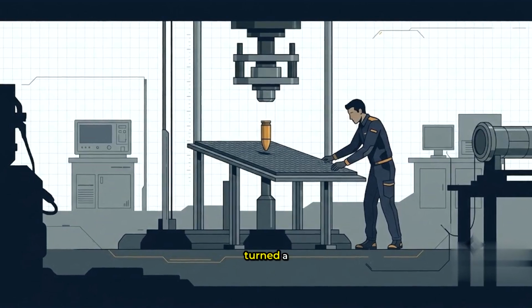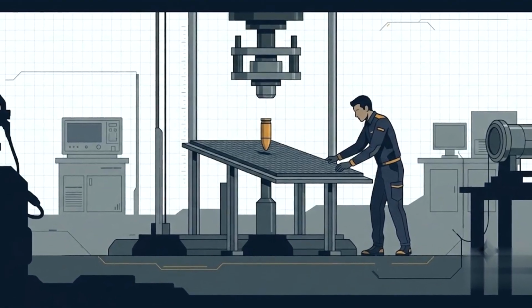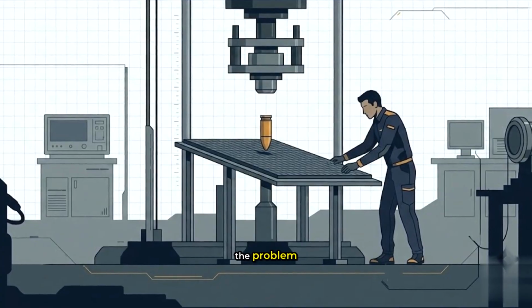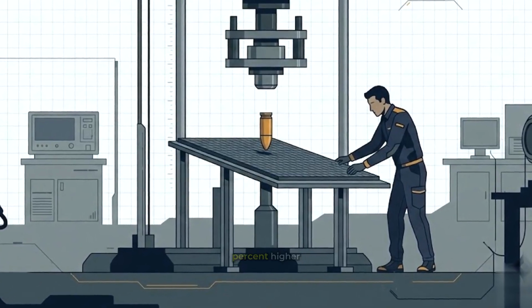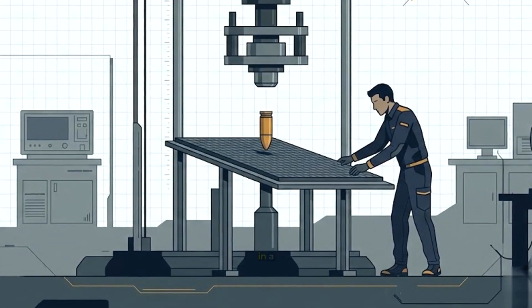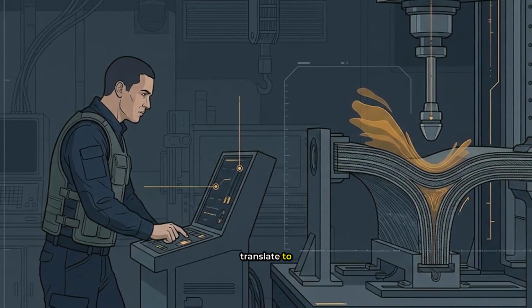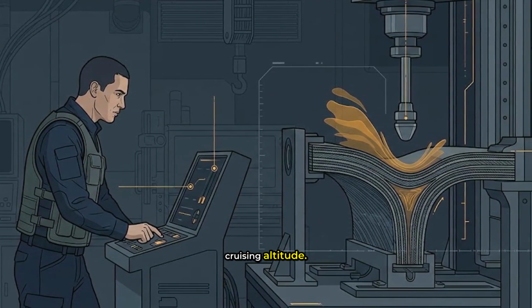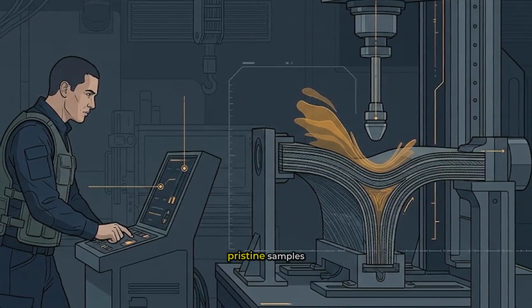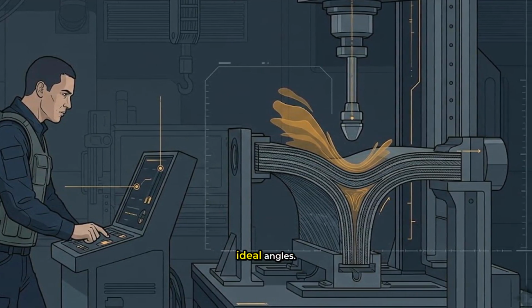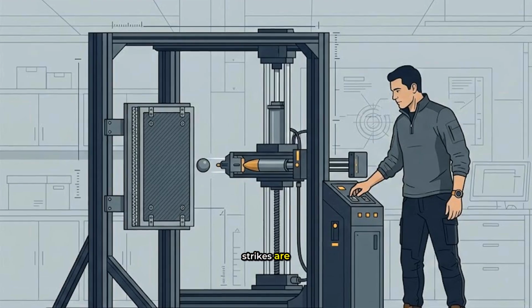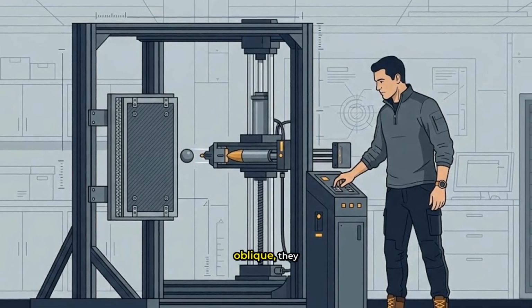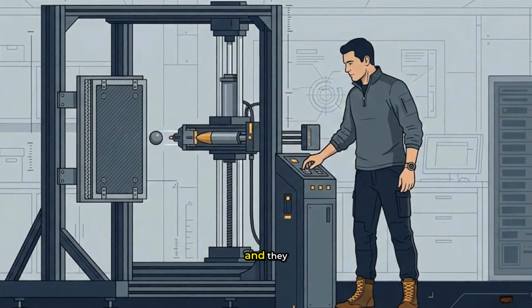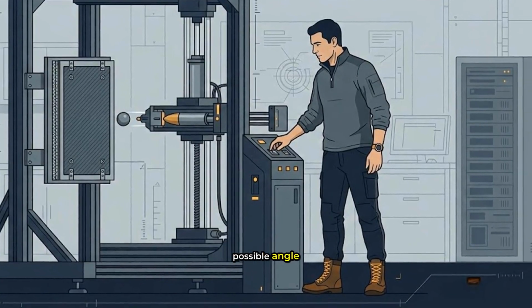Graphene skins turned a bird strike nightmare into a survivable event. Here is the problem with the headline. 60% higher impact resistance in a lab test does not translate to bird-proof at cruising altitude. That number comes from pristine samples struck under ideal angles. Real bird strikes are never ideal.